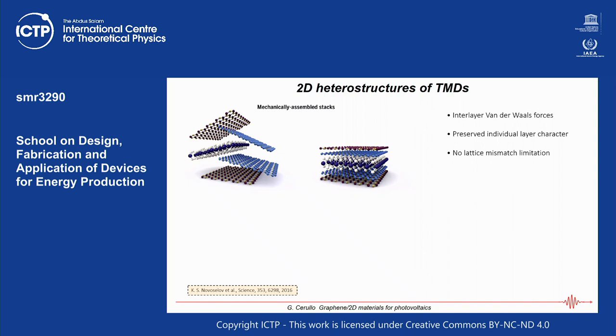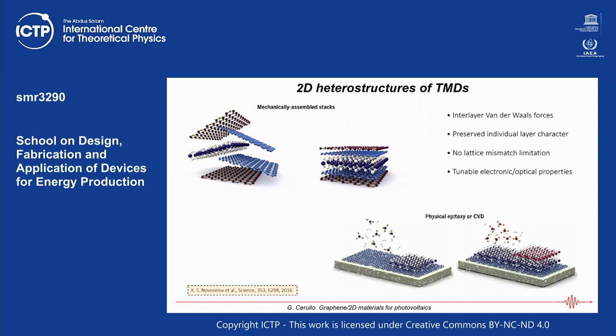When making conventional semiconductor heterostructures in optoelectronics, you need to account for lattice mismatch between different materials, which limits capabilities. But here, because of the van der Waals interaction, you have no such limitations. If you can assemble these heterostructures, you can really put together many different materials with almost unlimited freedom, making many different devices consisting of heterostructures of two-dimensional semiconductors.